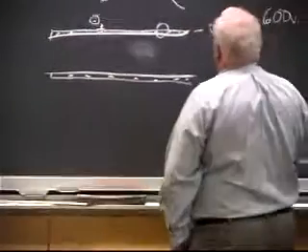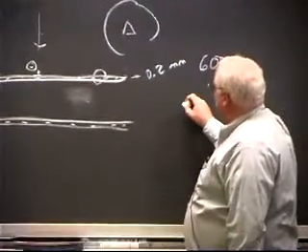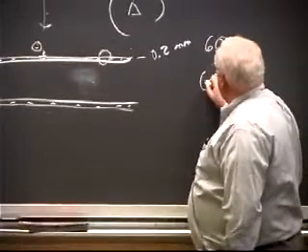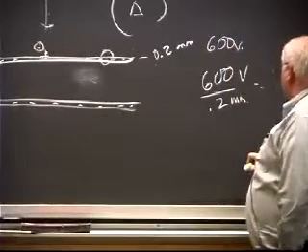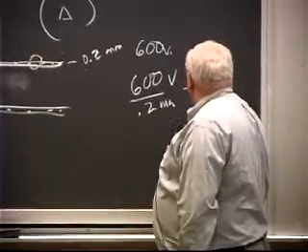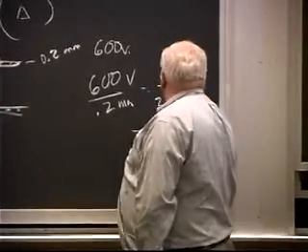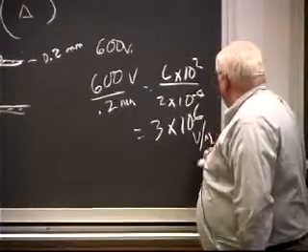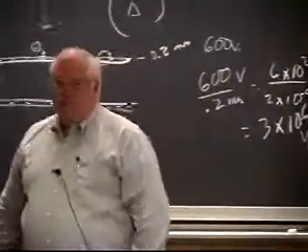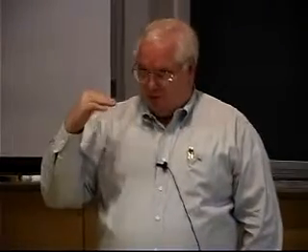And I basically said, well, what's the field gradient across here? If I've got 600 volts across 0.2 millimeters, that works out to 6 times 10 squared over 2 times 10 to the minus 4, and that's 3 times 10 to the 6th, if I did that right, volts per meter. And these were very, very sharp particles. Basically they were getting field emission that was putting a charge on there as they applied the voltage, and it was because of these sharp particles on the surface.